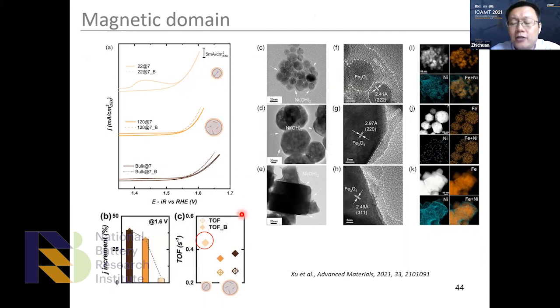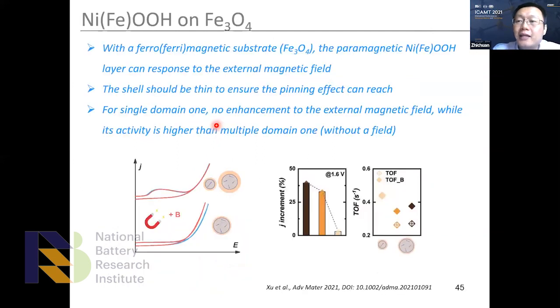And also we found that without a magnetic field, a single domain particle can actually reach the highest activity, just like before. Even without a magnetic field, they can have the highest activity, because it's pretty much like the status of magnetization. So this is actually consistent with what we have observed. If we apply magnetization, the multiple domain particle will become single domain, and then the activity will approach the single domain particles. And this actually indicates much more for mechanism investigation, right?